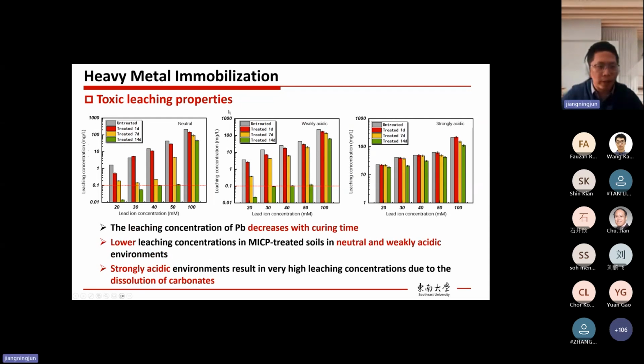Then for the toxic leaching properties, we tested under 3 different conditions: the neutral condition, the weakly acidic condition, and the strongly acidic condition. Because we know the calcium carbonate precipitation is very vulnerable to acid, normally we don't expect it to work under acidic condition. Then from this test, we see similar phenomena. For the neutral condition, after 14 days of treatment, except the 100 millimole, the most severe case, for all other cases, it is below a leaching concentration of 0.1 milligram per liter. This is a Chinese standard for type 4 groundwater. So all cases could almost meet it.